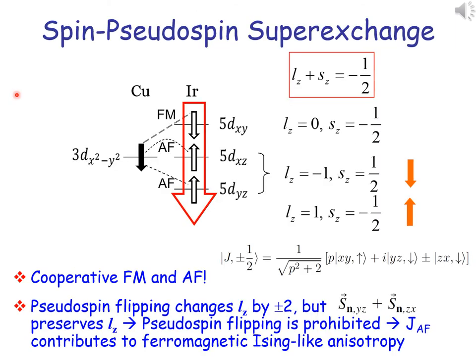However, the low-energy physics in the copper-iridium oxide is described by the super-exchange between the copper spin and the iridium pseudo-spin. For an iridium pseudo-spin, the real spin of the hole partially occupying the XY orbital must be opposite to that in the XZ-YZ orbitals. Looking at the ferromagnetic alignment of a copper down-spin and iridium down-pseudo-spin, this ferromagnetic exchange and this anti-ferromagnetic exchange interaction between real spins become cooperative, and the system exhibits ferromagnetic order.